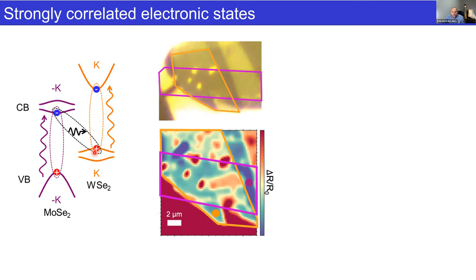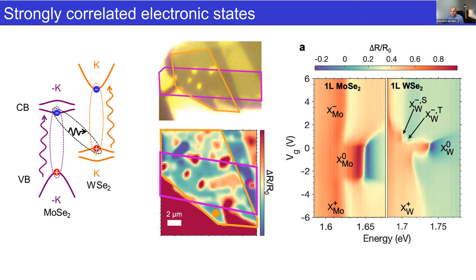So again, this is now another micrograph of our sample. We can see that there's these bits of debris, which I think are small flakes of another monolayer on top. And if we take a reflectivity map of the interlayer exciton, we can choose the resonance and basically make a map of the sample with a particular resonance. We see it corresponds quite well with the optical micrograph. And so as well in the sample, we have additional monolayer only regions that you can see here where the orange dot and the purple dot are. And so we can first probe these regions as a function of doping. And it looks something like this for the molybdenum diselenide region and for the tungsten diselenide region where we have a neutral regime.